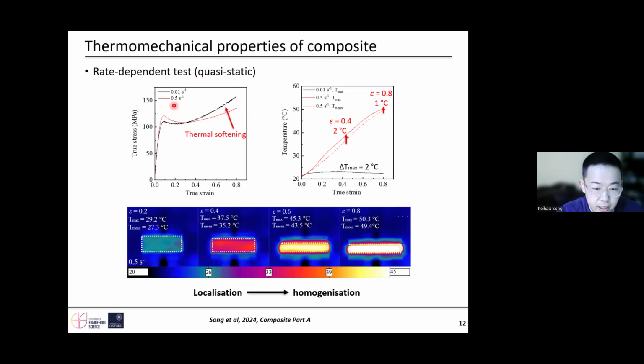Not surprisingly, the higher strain rate gives you higher yield stress, but at the higher strain, we can see the 0.01 per second test exceed the 0.5 per second test. The reason is, in the 0.01 per second test, we can get only a 2 Celsius temperature rise. However, for the 0.5 per second test, the temperature rise is about 30 Celsius. So that's the reason that causes the thermal softening for 0.5 per second.